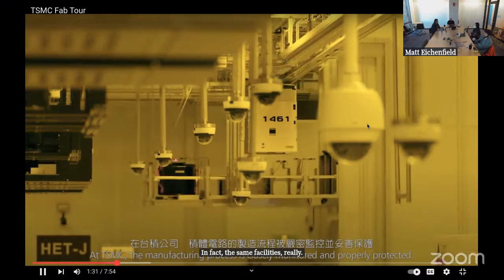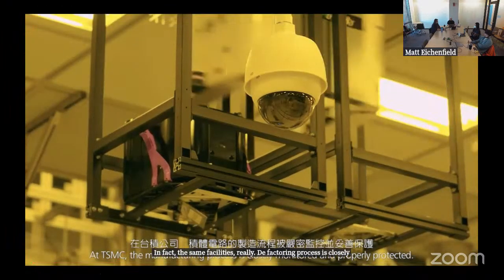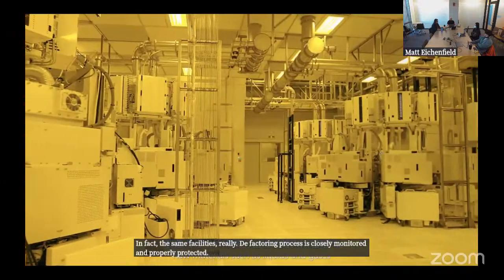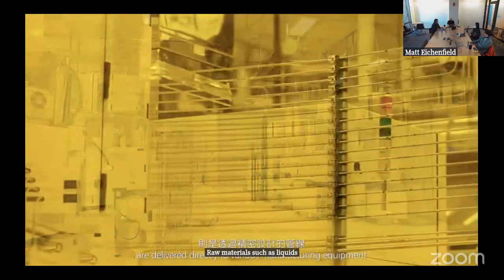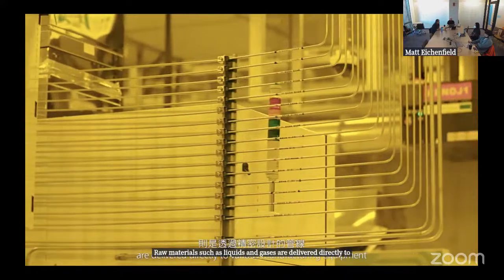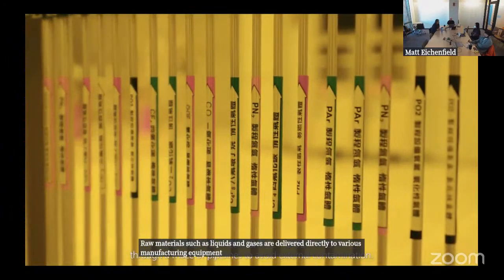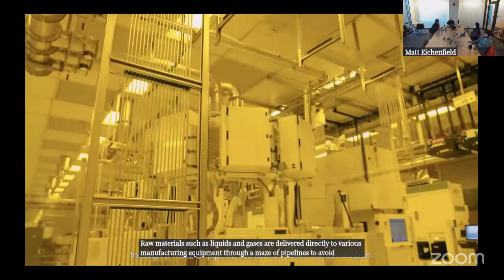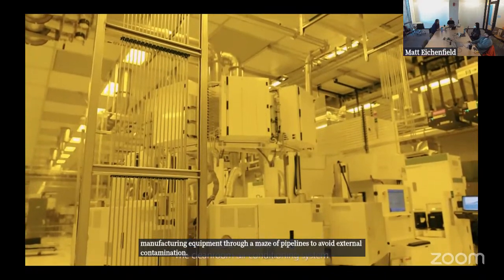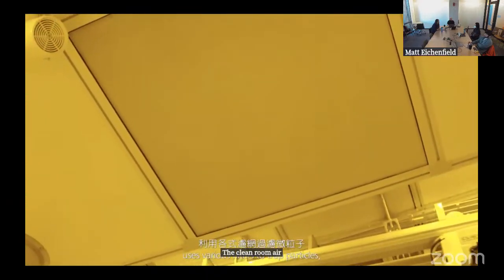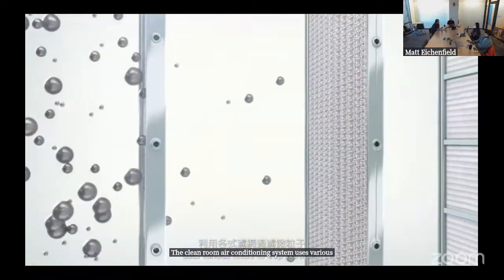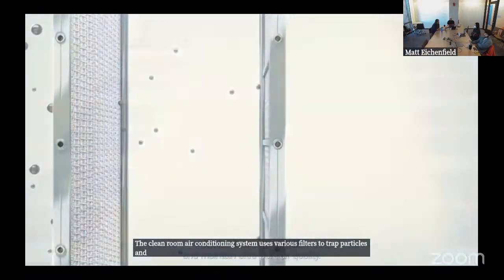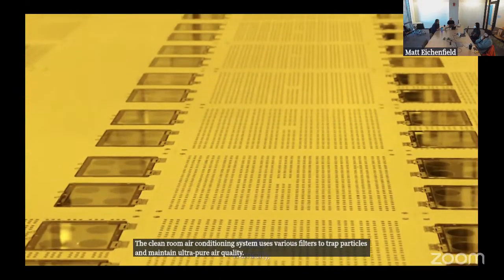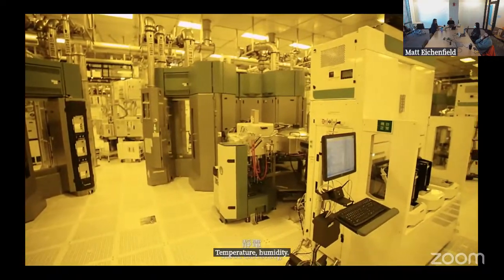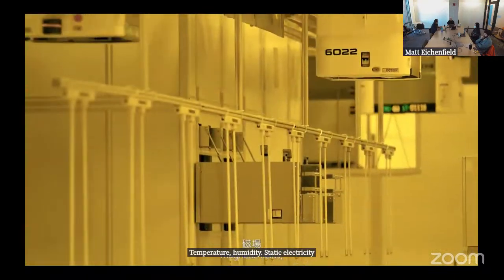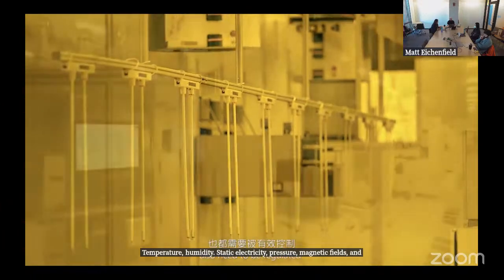The manufacturing process is closely monitored and properly protected. Raw materials, such as liquids and gases, are delivered directly to various manufacturing equipment through a maze of pipelines to avoid external contamination. The clean room air conditioning system uses various filters to trap particles and maintain ultra-pure air quality. Temperature, humidity, static electricity, pressure, magnetic fields, and vibrations also need to be regulated.